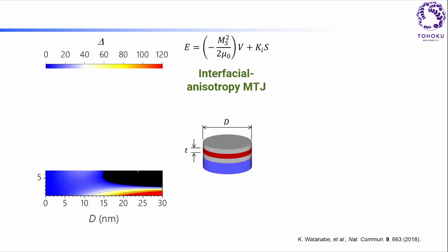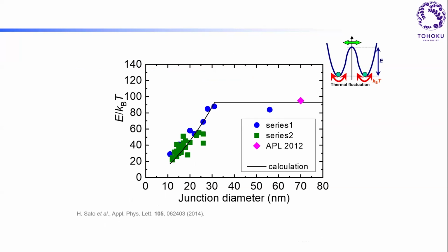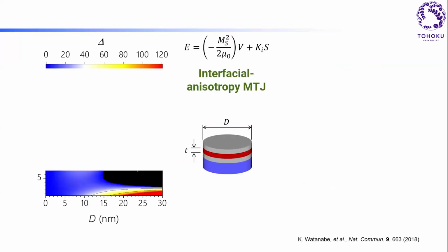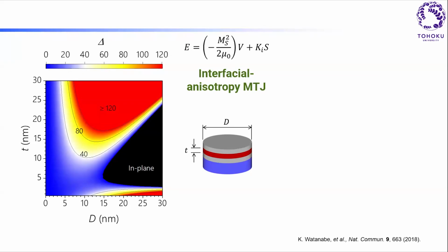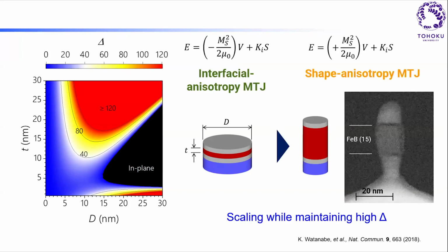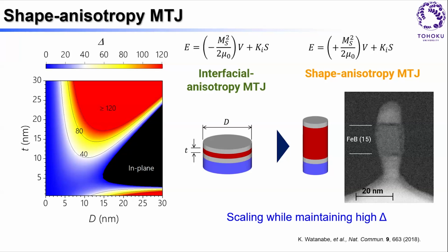But people wanted to see whether we can go further in dimensions. People didn't like this drop of the curve because it means that our technology approach is not scalable. So we came up with an idea of utilizing a thick magnetic layer, basically making it very thick and converting this minus sign to plus sign. In this case, shape anisotropy was against us, but here shape anisotropy is with us. And basically, we made a very small bar magnet, and that worked very well.